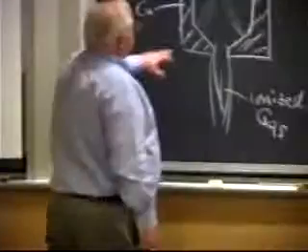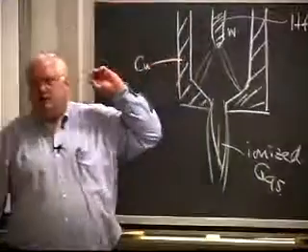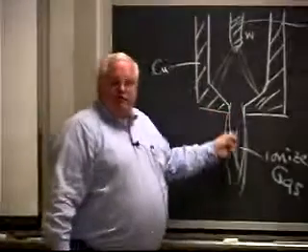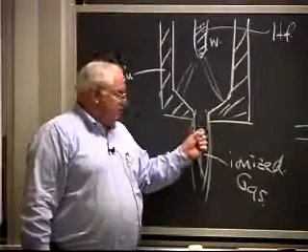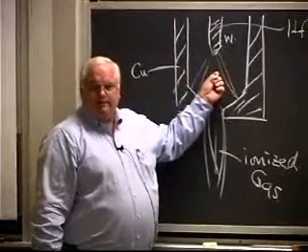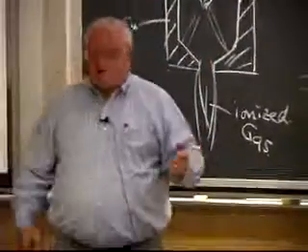It turns out hafnium forms a refractory oxide, HfO2, which also has a slight electrical conductivity. And so you can get a hafnium electrode that even when it oxidizes will still carry enough current that you can basically use oxygen as your shielding gas. So now we have what we call plasma cutters, and instead of an oxyacetylene flame, we essentially have a very rapid gas jet, a compressed air jet, which is heated by a plasma flame up here in this constant volume chamber, and shoots out at very high velocity. And it can melt through.